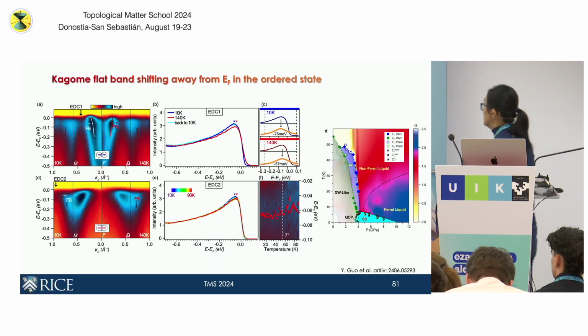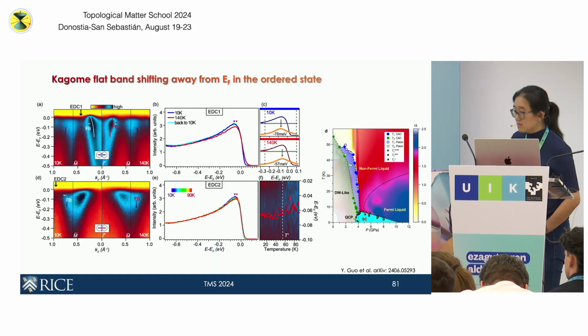The pressure suppresses these density wave-like orders. Maybe that suppresses the shift so that there's a larger participation of the flat band when the superconducting dome appears, right? So as a bulk material, I think this is an interesting system to consider in the potential involvement of the Kagome flat bands in the superconducting dome. But a lot more work needs to be done to really look at this relationship.